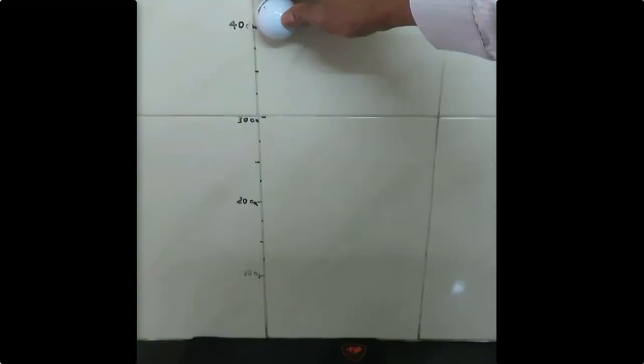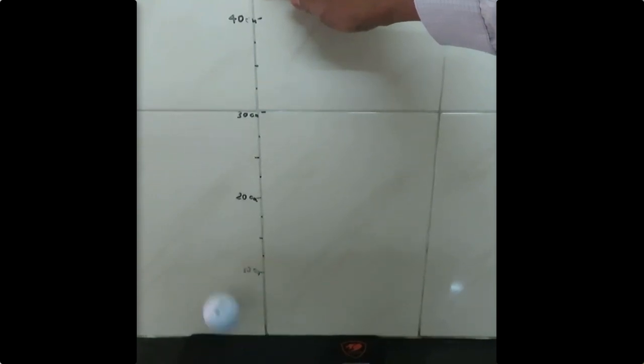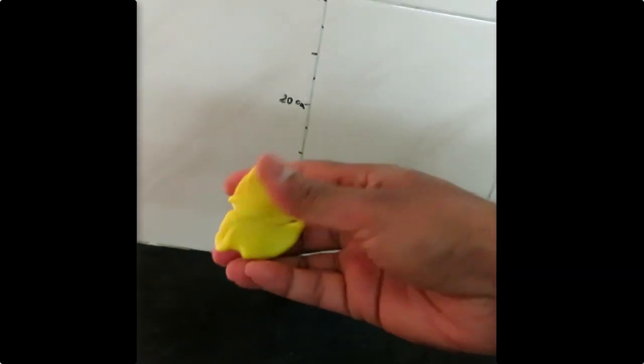Now, I am putting a computer mouse pad, which is soft, and then dropping the same ball from the same height of 40 cm. This time the ball has rebounced back to a height of only 19 cm. This shows that the loss of energy is more in this case. This loss is because of the viscous effect in the material of the pad, which is made of soft polymer foam. This is the damping effect of a polymer.